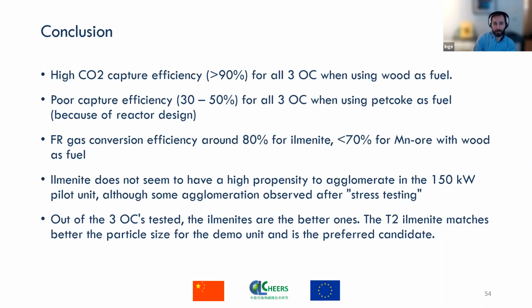Yeah, the fuel reactor gas conversion efficiency was around 80% for ilmenite, but below 70% for the manganese ore with wood as fuel. And ilmenite does not seem to have a high propensity to agglomerate, at least not in our rig, although some agglomeration was observed after stress testing. So out of the three oxygen carriers tested, the ilmenites performed better, and the ilmenite T2 matches the particle size of the demo unit and is therefore the preferred candidate.